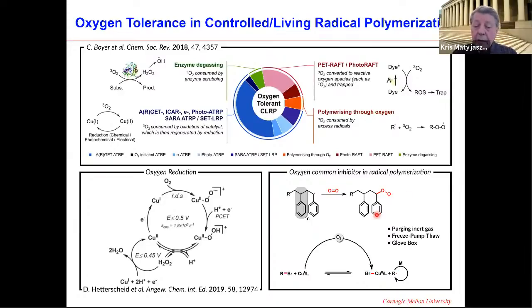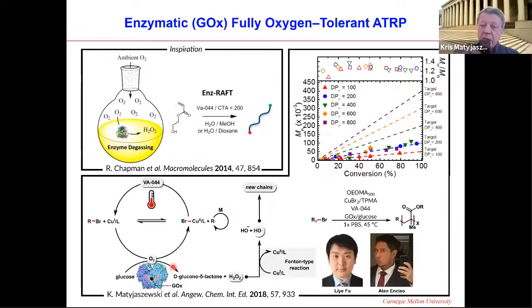In the case of copper, oxygen can also oxidize copper 1 to copper 2 species and the reaction would stop. You may also take benefit of this reaction. This is a paper from last year showing the oxygen reduction reaction with exactly the same copper TPMA system. So there is the oxidation of copper 1, formation of this peroxy species in the presence of protons. Eventually you can produce hydrogen peroxide under these conditions. So this is a really interesting possibility, but how can we degas the system in the easiest way?